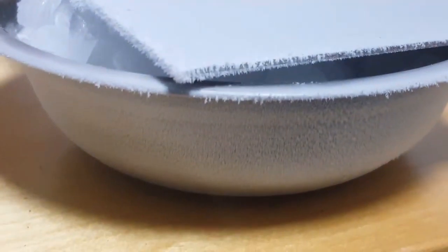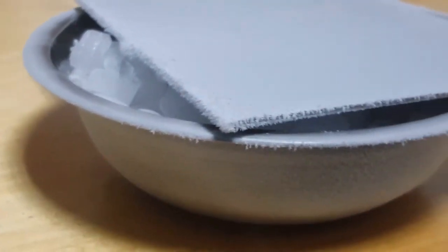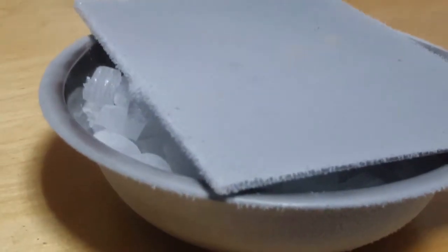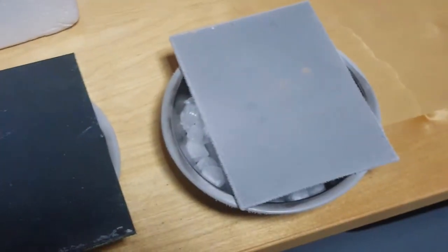You can see all the bowls have condensated, and the condensation has refroze on the outside due to the ambient temperature and humidity of the room. And on the flip side, the two coated samples have actually kept the dry ice in those bowls from melting as quickly as the dry ice is in the bowl with the blank metal sheet on top. So it works both ways with the transfer of heat.